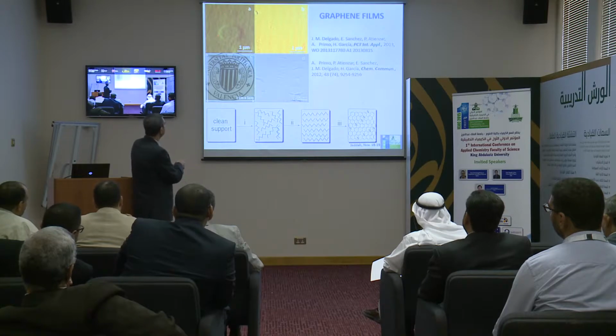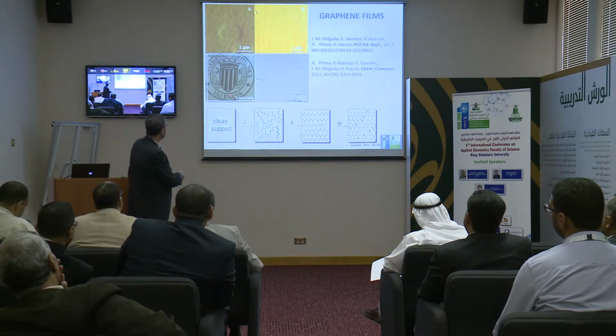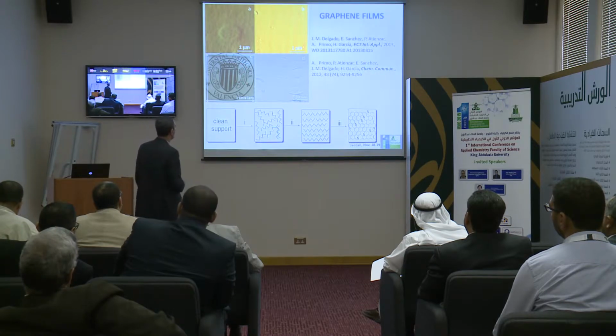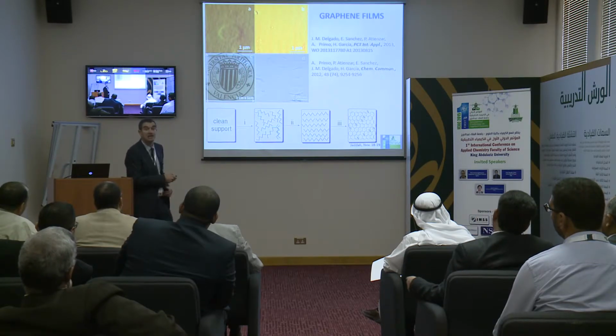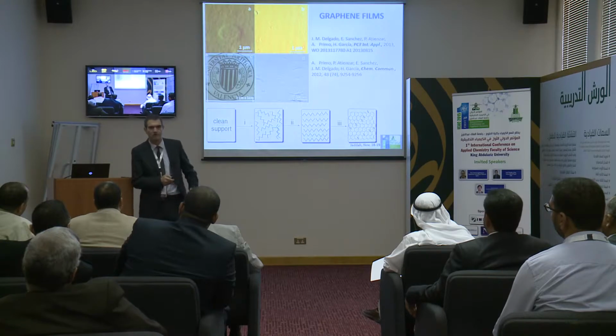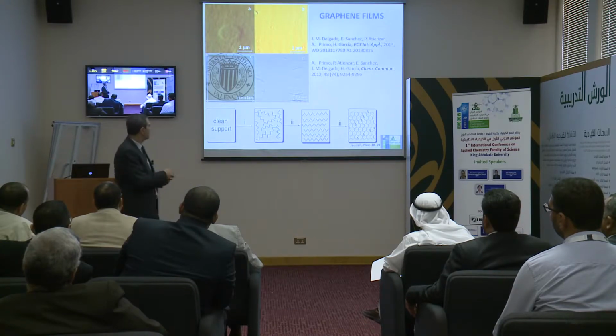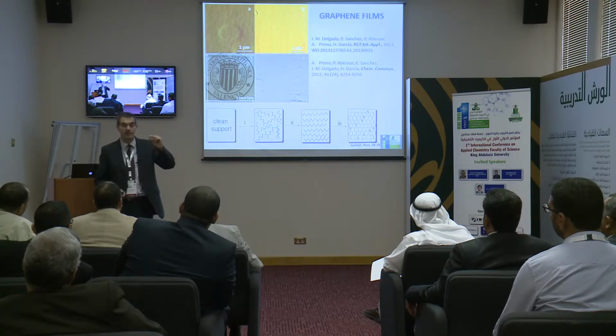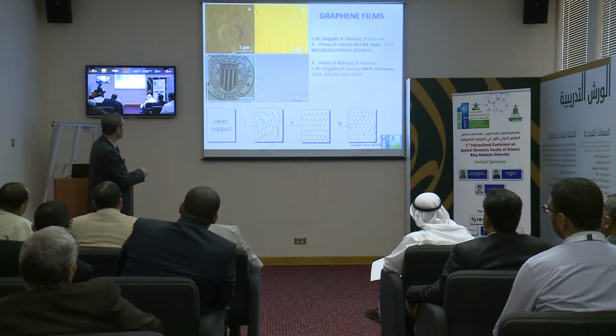So this is the precursor. This is another image of the precursor, and when we heat and we pyrolyze, sorry for this, then we obtain the graphene. So this is the biopolymer, and here we have the graphene with the logo of our university. And if you have single layer graphene, you don't see anything at all. It seems that there is nothing. So here what we have is 4 layers graphene, and with 4 layers graphene you start to see some gray tint, gray color on top of this.